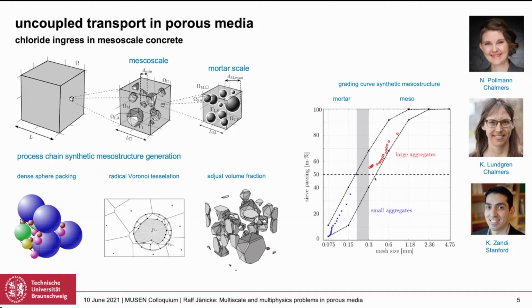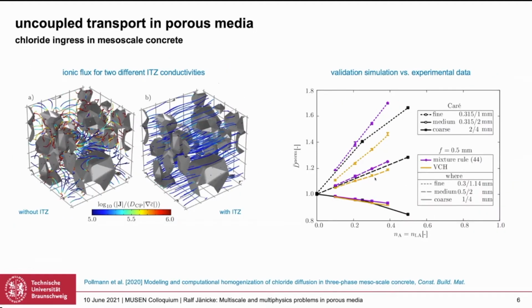Okay, and based on that, now we can do our simulation. The model itself is not so super fancy here because it's just diffusion, but diffusion which takes place in the volume plus at an interface. Without diving into the equations here, what I have displayed here is the ion flux in the case of an absent interfacial transition zone, so this pre-damaged layer. And here, this streamlined one where this interfacial transition zone is very dominant. And obviously, you can expect that here the conductivity, or diffusivity, will be way higher. And based on these RVE studies, we were able to introduce a very simple macroscopic material model, which we could fit to experimental data and then also use to predict the experimental data for other examples. So we were able to validate that.